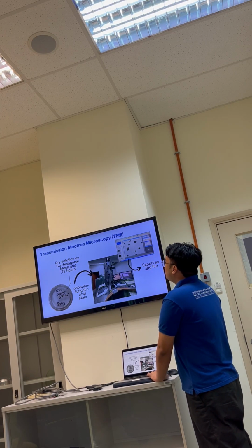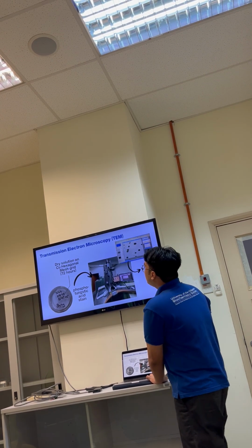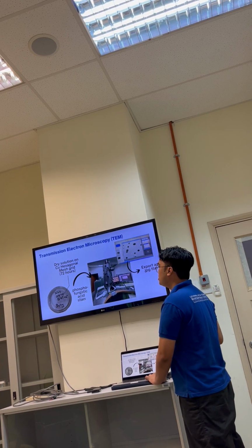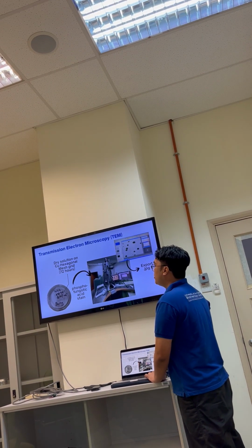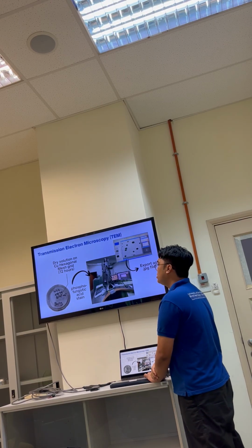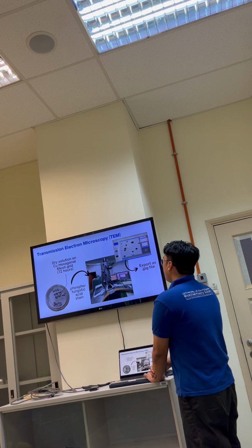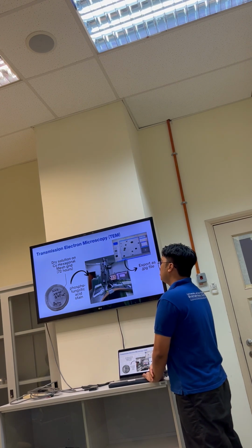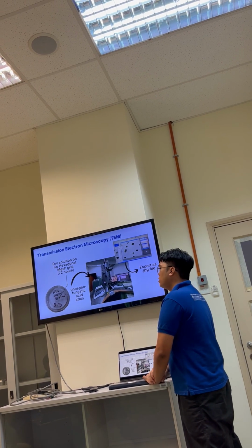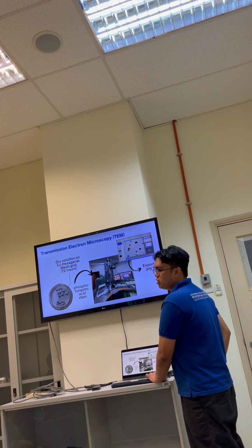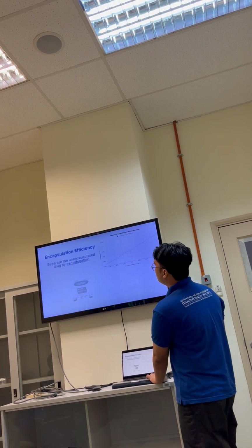Then we also get this in TEM, the transmission electron microscopy. So a small drop of the NLC solution was allowed to air dry in the copper hexagonal mesh grid for 72 hours and was stained with 1% phosphotungstic acid stain. And this was viewed in the Faculty of Medicine. And of course, the JPG file was exported for our analysis later on.